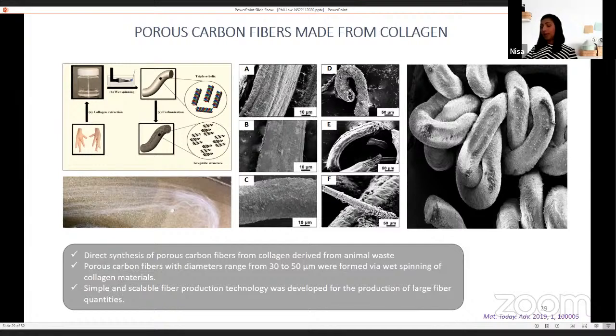Together with CSIRO, we have successfully established sustainable and environmentally friendly methods to extract collagen from chicken byproducts. And we use that extract to make carbon fibers, and we came up with highly porous carbon fibers. These are the SEM images. You can see that the fibers we created were very flexible. In our approach, we use very environment-friendly materials and processes to create opportunities in the circular economy. We are continuing this research, and we have come up with not just porous carbon fibers, but we also find that the approach is very beneficial to make sensors and similar kinds of value-added materials from these waste products.